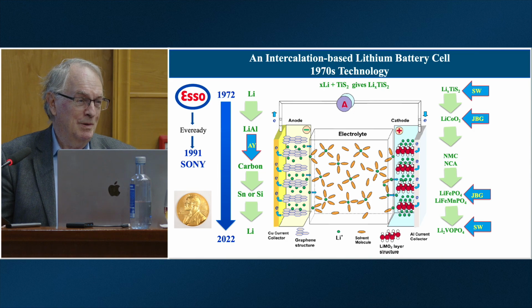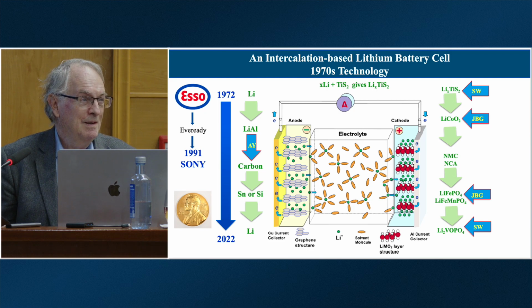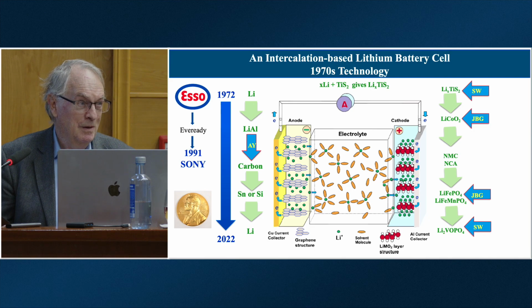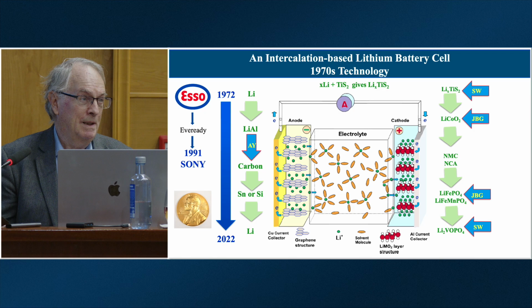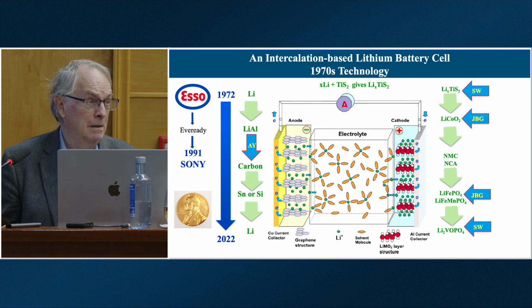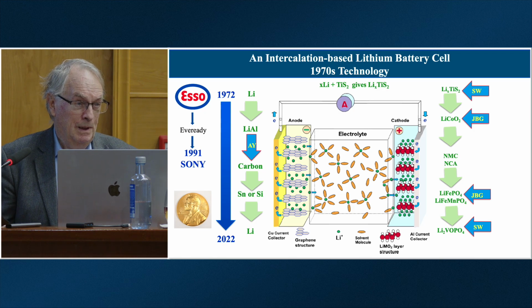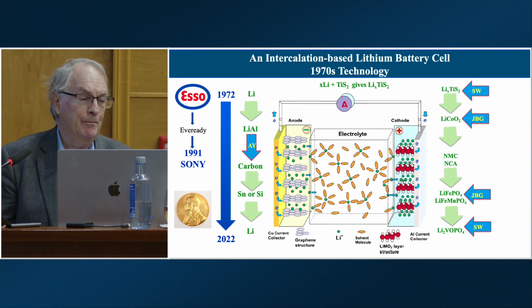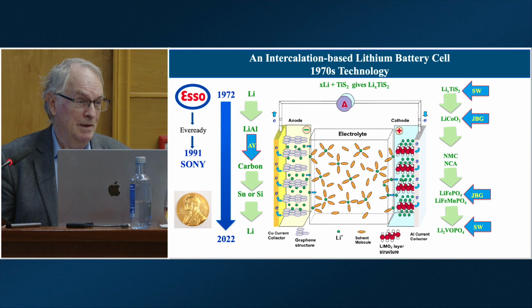No, this was the obvious, cleanest way to go, but if any of you have done electrode deposition, you'll know metals tend to plate in the dendritic form, so you form dendrites that short the cell out. So what we did, we switched over to aluminum metal. Lithium reacts with aluminum 1-to-1 at room temperature, and that worked well for maybe 10, 20 recharges, clearly not viable long term.